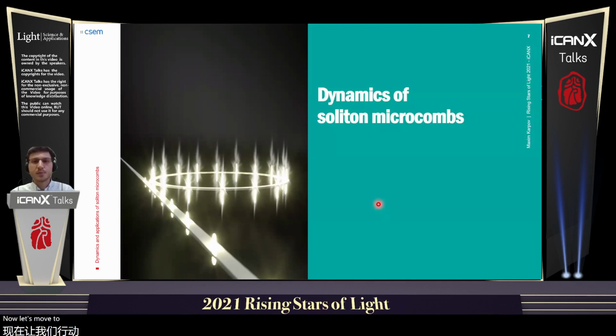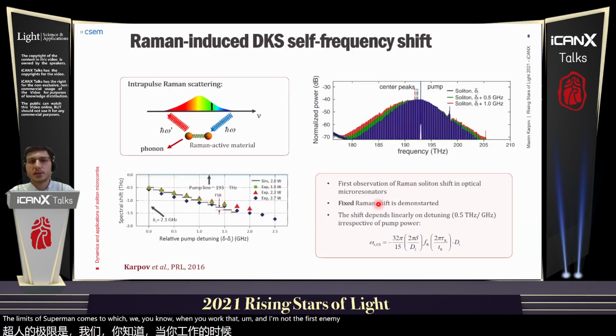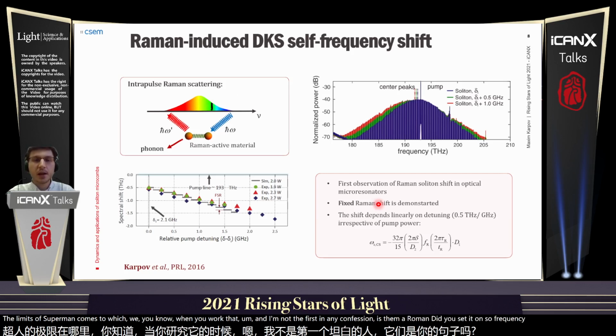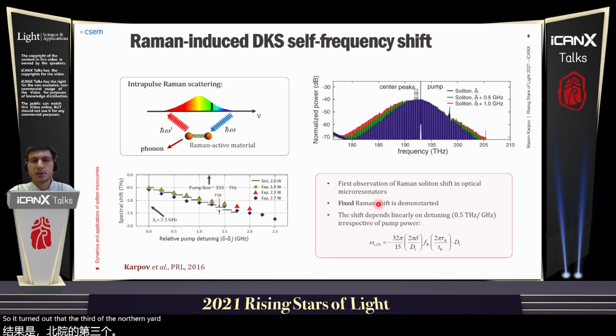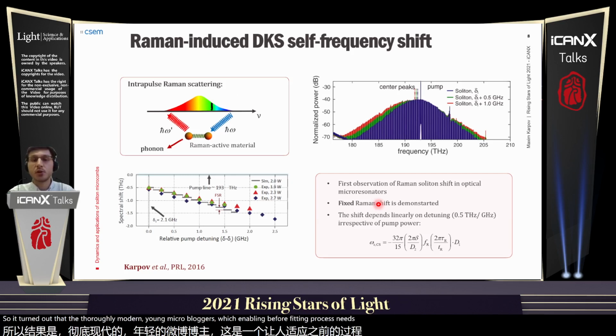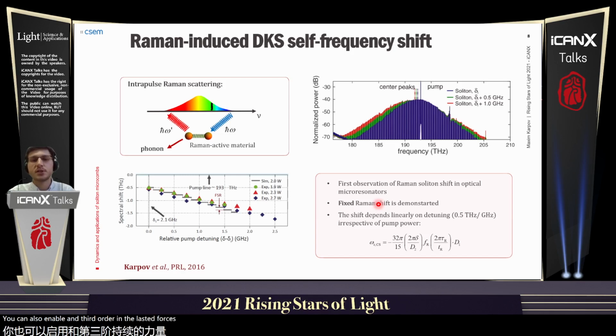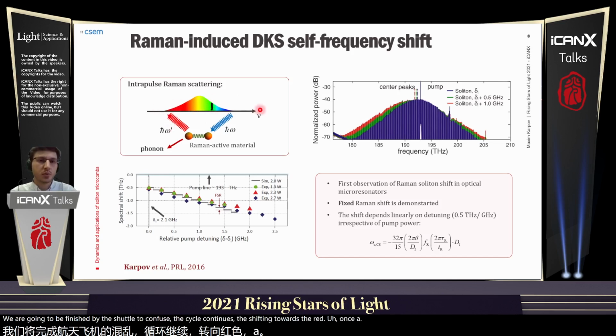Now let's move to the dynamics of soliton microcombs, which we worked on. The first dynamical effect is the Raman-induced soliton self-frequency shift. So it turned out that the third-order nonlinearity in microresonators, which enables the four-wave mixing process, can also enable some third-order inelastic processes, such as stimulated Raman scattering. And this stimulated Raman scattering usually happens within the pulse, where it essentially takes the photons from the high energy part of the pulse and transfers them to the lower energy part of the pulse with the emission of a phonon. And this process is actually very well known in optical fibers, where it results in a continuous shift of the soliton spectrum with respect to its initial position. So the spectrum continuously shifts towards the red as the soliton propagates inside the optical fiber.